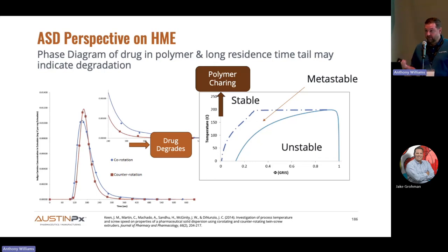There's quite a few products made by this process, but a couple things that you can point out here from a kinetic standpoint and from a unit operation standpoint is there's these potentials for long residence time tails. And so one of the things when you think about scaling up and doing high throughput processing with KinetiSol is there's not really a residence time distribution. What we do is we break the blend up into pieces, and then we apply a specific timed energy event to it, which is very short, and then we just repeat that over and over again. And so we don't have this disparity between the material that came out here and this material that might still be in the machine 3, 4, or 5 minutes later. This is a significant potential for drug degradation, one of the reasons why extrusion can be limiting.